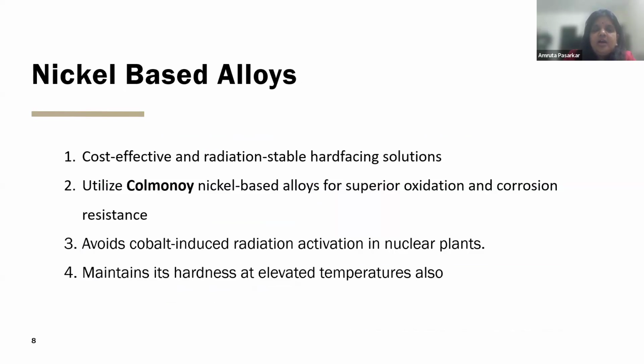Now, nickel-based alloys. Basically, cobalt-based alloys are prone to radiation. So wherever radiation is a concern, nickel-based alloys are used, as they are radiation stable and avoid cobalt-induced radiation activation in nuclear plants. Also, nickel-based alloys have very high hardness, and they can maintain it at elevated temperatures, as in nuclear reactors, around 500 to 700 degrees Celsius. We can also use nickel-based alloys for superior oxidation and corrosion resistance. Basically, nickel-based alloys are used wherever there are very high temperatures, as they can maintain their high hardness at elevated temperatures.